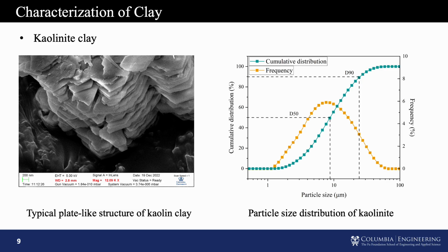Every single system I'm introducing today specifically focuses on one type of clay and one type of biopolymer. The clay we used in this research is kaolinite clay, as it is the most abundant clay on this planet. And you can see kaolinite is a plate-like particle, with particle size ranging from 1 to 16 micron. Why I'm showing this here is I want to tell you that the particle we're using is a micron-scale material. It's not a nanoscale material. So when we consider the particle interaction between colloidals, we can ignore the Brownian interaction.